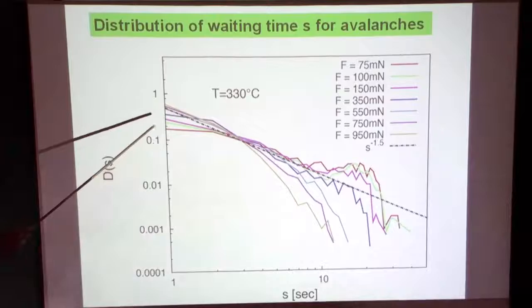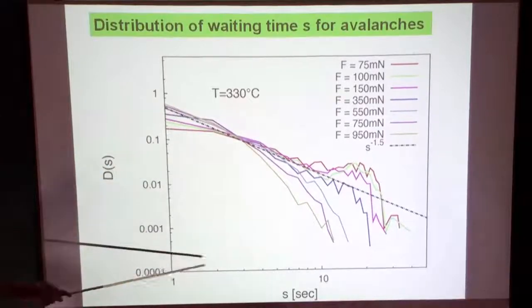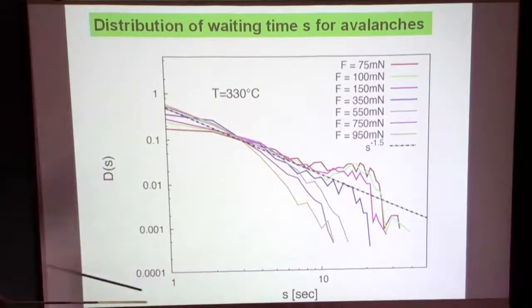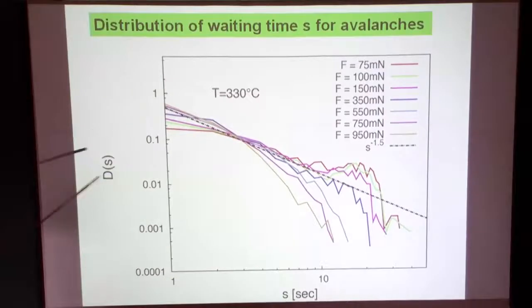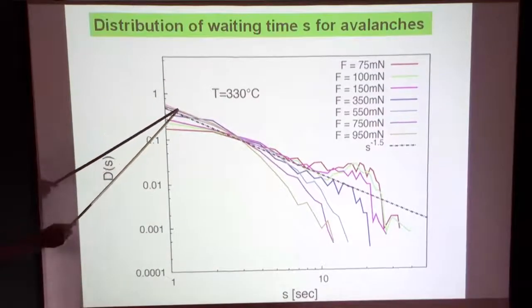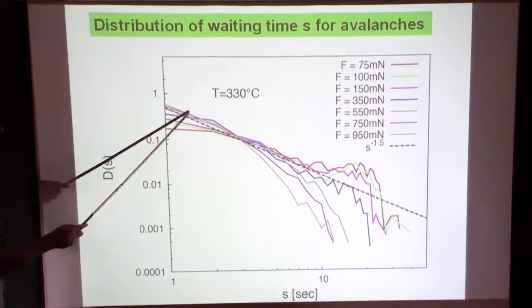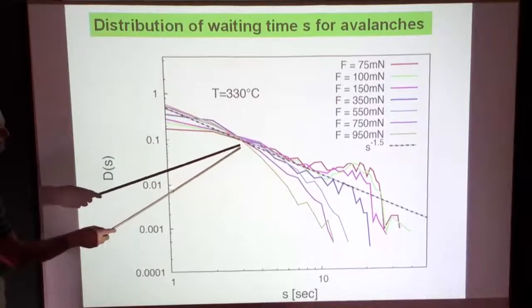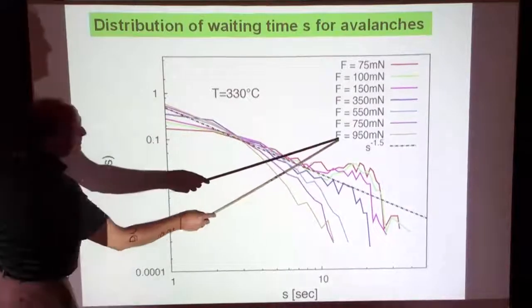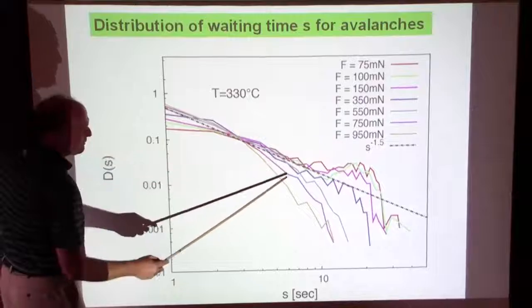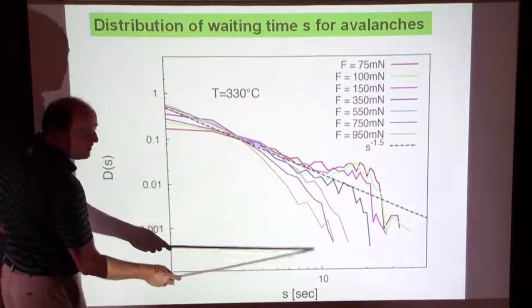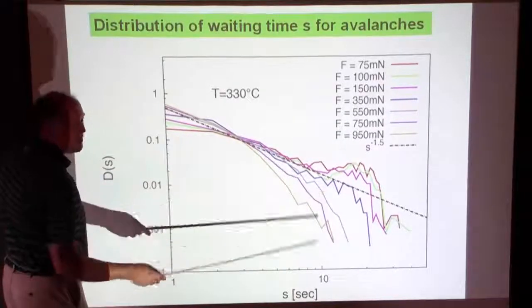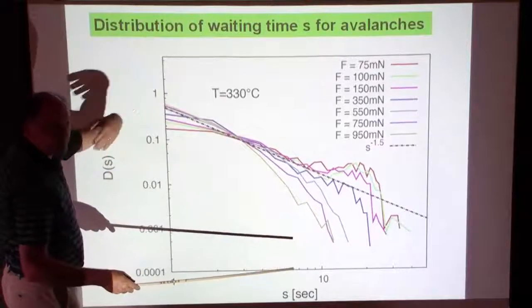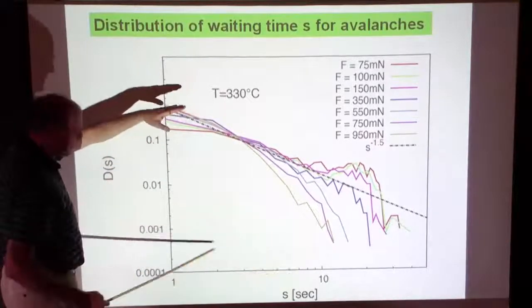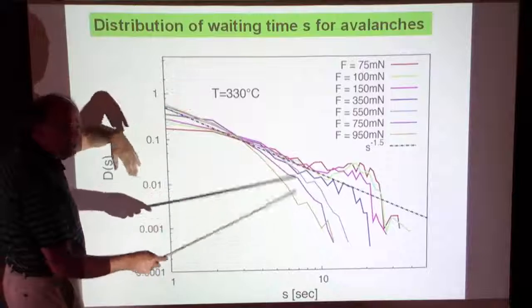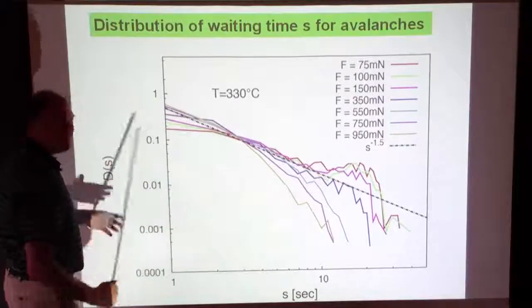And what we see is actually not so much. There is only limited time in the beginning. We have only 2 or 3 decades, actually. That's very limited data. I have to apologize for that. But it looks like we get this minus 1.5, and we get the cutoff. Here you can see these absolute numbers, but we come close to the yield stress already, and we cut off then these waiting times. We're coming closer to the yield stress. There are more events. The waiting time, which is put down here, is getting shorter and shorter, and then you get the cutoff early.